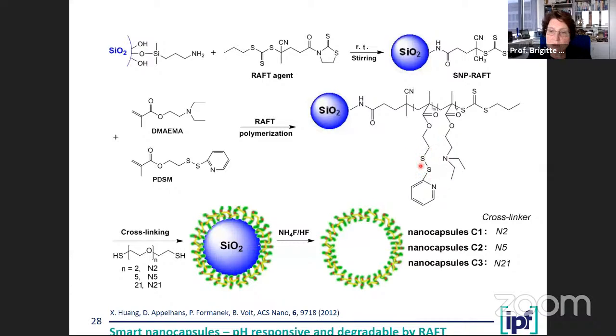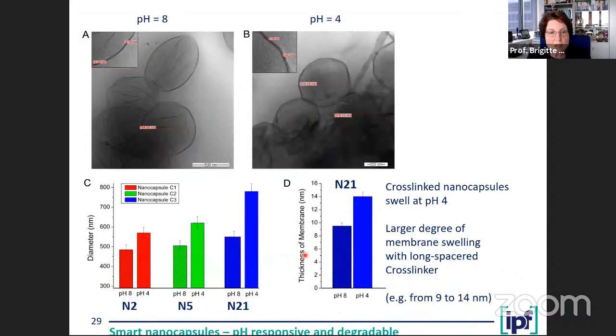For example, we introduced here disulfide units, which we then used for a disulfide cross-linking. And that is, of course, a cross-linking which is sensitive to redox reactions. And therefore, we can also disintegrate our membranes. Now, first you see nice capsules, beautiful capsules. They are very nice and stable. The swelling depends a bit on the cross-linking. So when you have a larger cross-linker, you get more swelling. And it depends on the pH, of course.